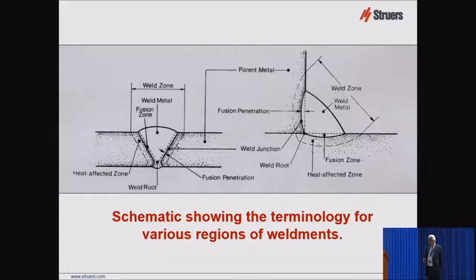But you can see the pointer. Here's our weld bead and our melted area on each side and the heat affected zone and then the base metal out here. And here's an angular weld and you can see the penetration is not very deep in either of those plates, which can cause problems.